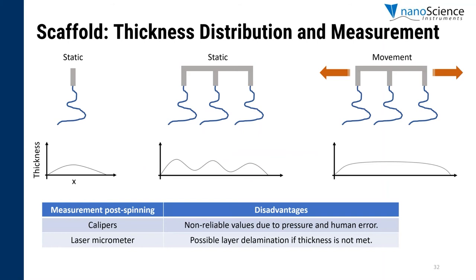Anyone with experience in electrospinning knows that sample uniformity and thickness measurement is not easily performed. The typical thickness profile when a needle tip is in the static position is depicted in the first diagram. You have a thicker area in the middle and then less deposition in the sides. So to avoid that from happening, what people usually do is use more than one needle tip at the same time. But the end sample may not be uniform, as multiple fluctuations throughout the sample can be seen. That's why you see three bumps in the thickness.